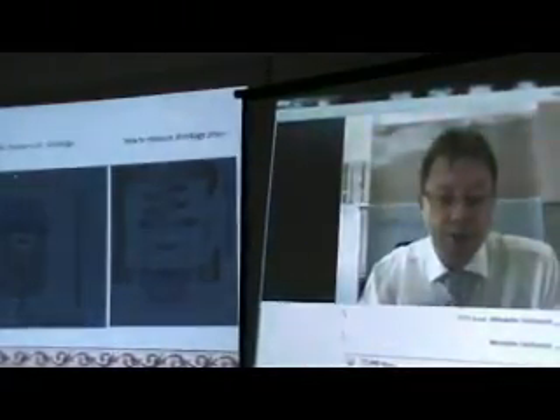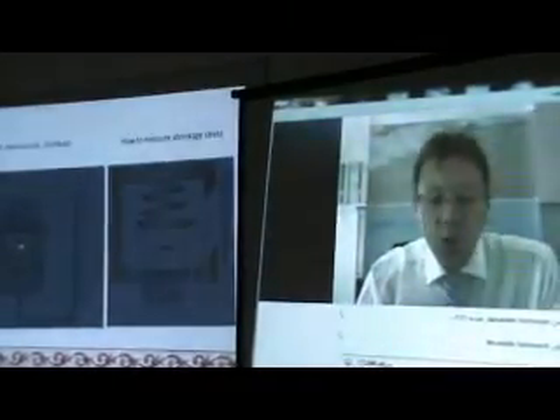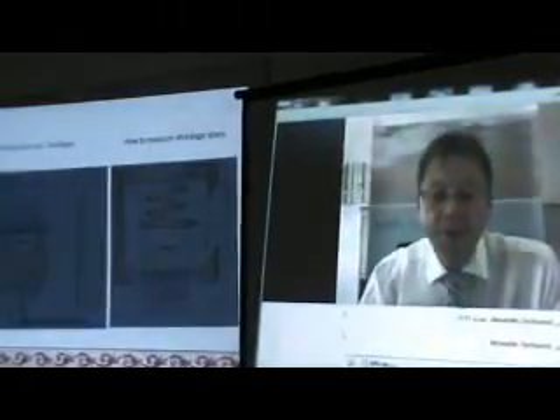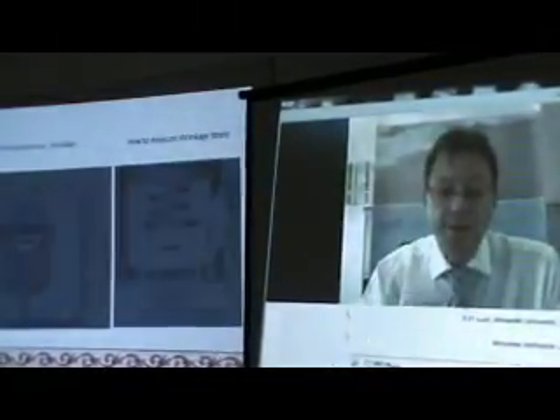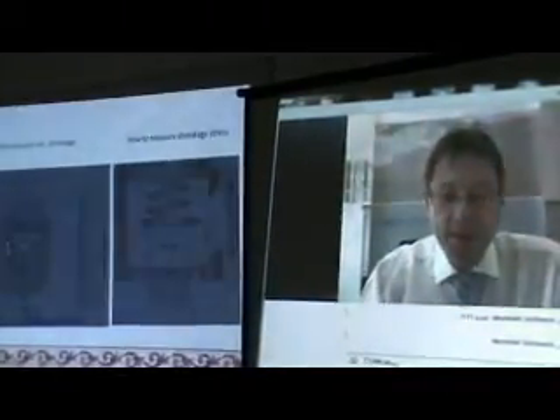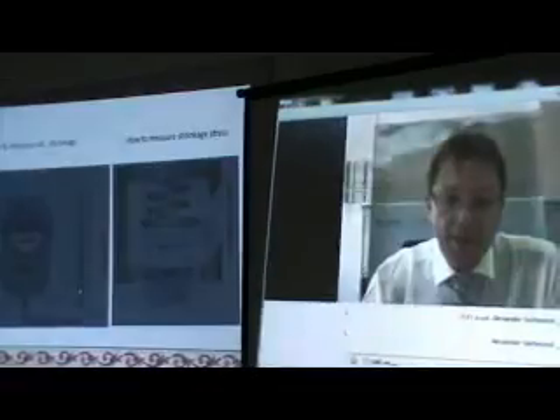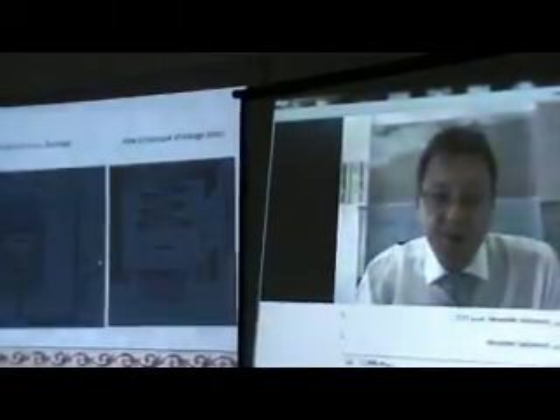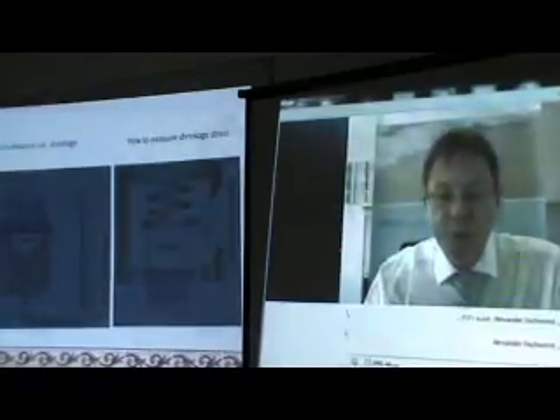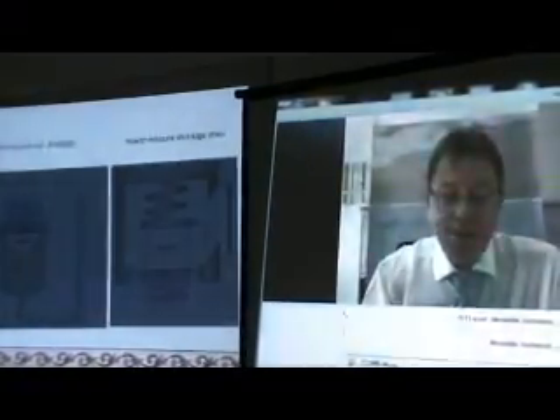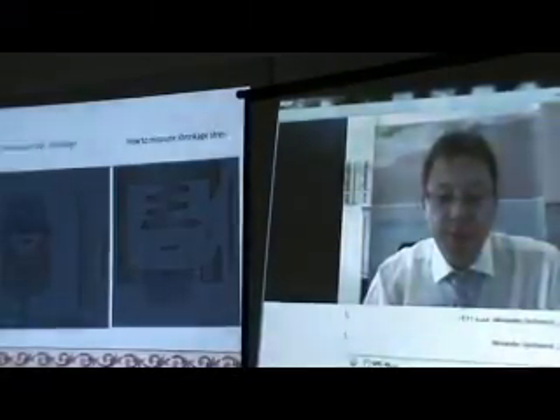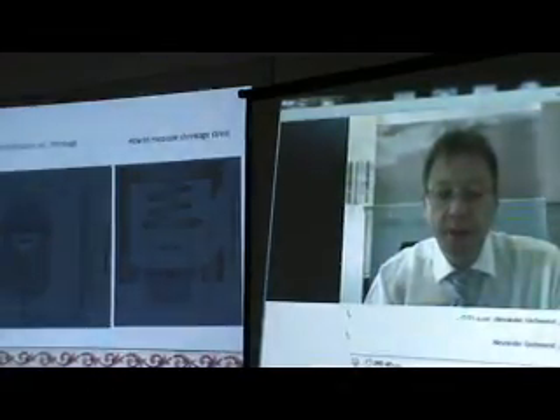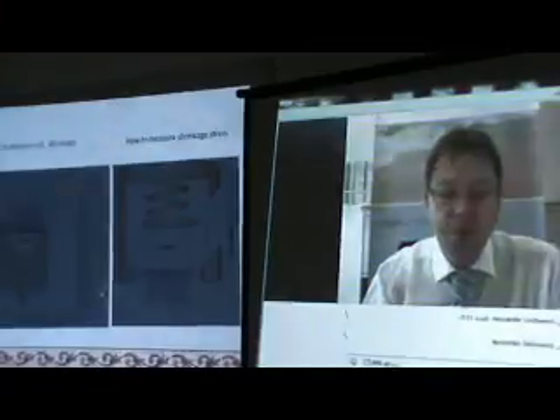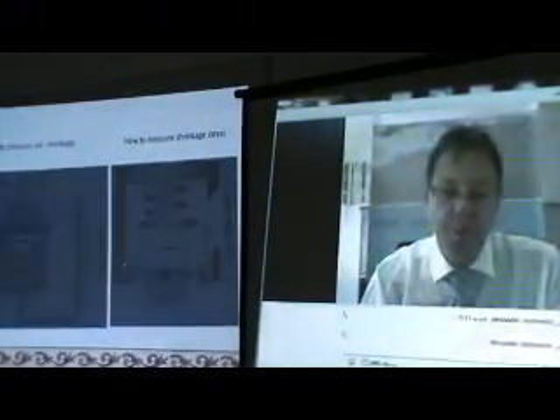To measure the volumetric shrinkage, a composite will be glued to a transparent glass plate. Then the container which you see there will be filled with a liquid, usually mercury. After that, the composite will be light cured through the glass plate, and then the chemical process will start. The molecules will go closer together. There will be an empty space created in the composite due to the fact that the molecules go closer together. The empty space will be filled up by the liquid, and therefore on the scale which you see on the right, at the university they can measure the volumetric shrinkage of this specific composite.